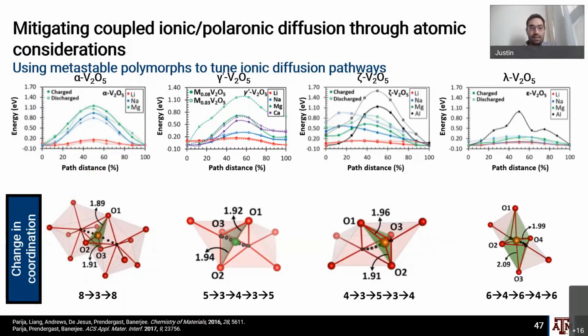And so, as you would expect, as lithium, for example, diffuses through these lattices, we've done a lot of theory to look at this. As I mentioned before, this 8 to 3 to 8 change in coordination environment that lithium undergoes as it diffuses through alpha V2O5 is very stark and precipitous in the way that it drops off, and this presents a large ionic diffusion barrier. But as we go into gamma V2O5 and zeta V2O5, these changes in coordination environment change in 2 ways. One, there are fewer bonds that break and form as the lithium ions diffuse, and that gives us smaller diffusion barriers. You can see here much lower for zeta V2O5 in particular in this third one. But then also the transition states they go through are a little bit larger, not as constricted, and so that also helps us a bit.